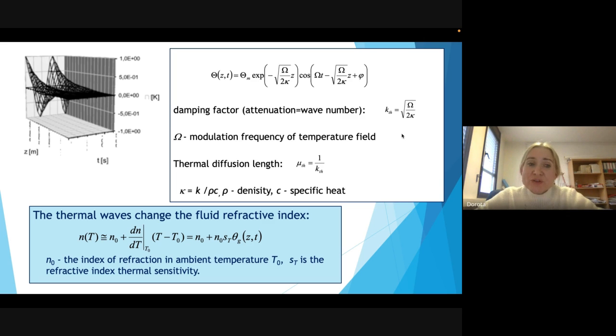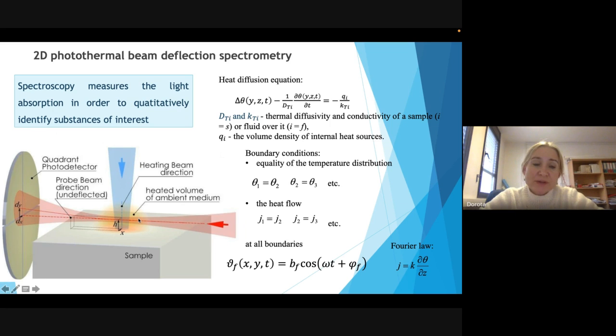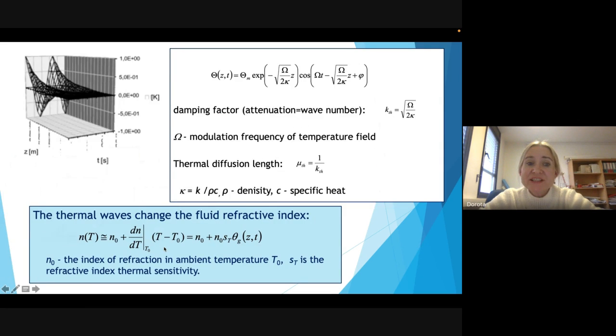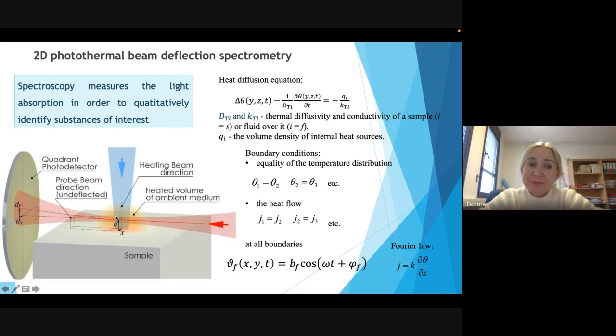So when we induce the temperature oscillation in the fluid above our samples, the optical properties of the fluid also change, especially we deal with the change in the refractive index of the medium. That change we further determine by another laser beam that is simply skimming the surface of the sample and probing the temperature oscillation induced in the fluid. And what happens to the probe beam, since it changes direction from its initial propagation, both in the direction perpendicular to the sample surface and in the direction parallel to the sample surface, it simply deflects in both these directions. That's why the method is called beam deflection spectrometry.